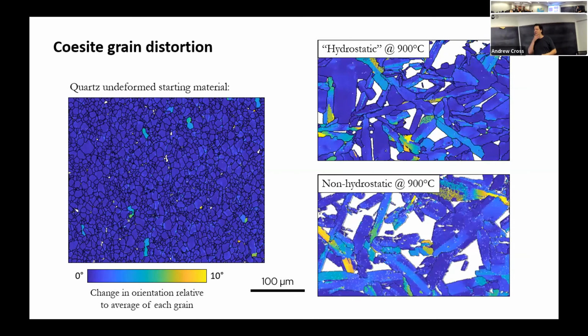But if we look at the coesite now, this is our nucleating phase. We see warmer colors. We've got these big laths of coesite, and those are actually quite beaten up inside, which we weren't expecting for a phase that's brand new and just forming. But we get all of these little subgrain boundaries, all the substructure that indicates that those crystals are being deformed.